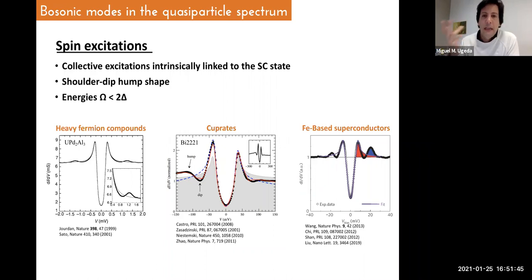These are collective excitations that are totally linked to the superconducting state, meaning that when they are in the superconducting state, they should show up, and when the superconducting state is killed, they should be killed with it. In general, in previous STM measurements, they have been shown as dip-hump shape features like the one you see here for this heavy fermion compound, also for cuprates and iron-based superconductors.